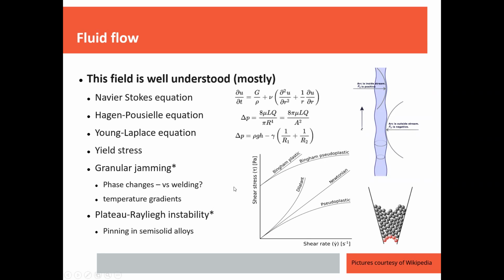There are some interesting considerations for granular jamming and for the plateau Rayleigh instability. I had a video of this. Unfortunately, I forgot to include it. But normally when you have a stream of fluid, it breaks up into droplets. That's what the plateau Rayleigh instability is about. But when you have a semi-solid alloy, the solid particulates appear to block the droplet breakup, which is very interesting. And then there's a combination of capillary forces and just a kind of defect pinning that prevents the droplet breakup.